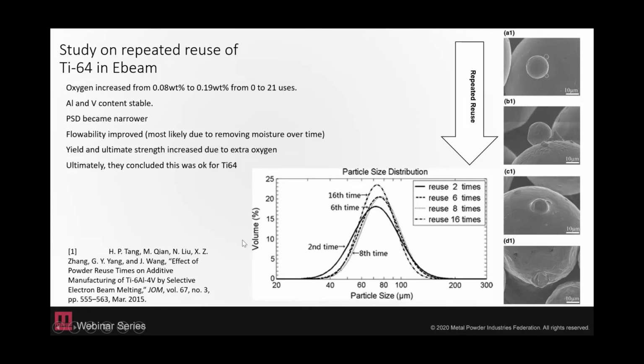So getting back to some issues with E-beam, here's just a study on powder quality that was done a few years back. They performed multiple builds with the same powder, and then they analyzed the powder after each build. So this study was being done with Ti-64, which is a popular titanium alloy. And so what they found in the study is that their oxygen did increase from their 0 to 21 uses. Their aluminum and vanadium content was stable, and they did see a narrowing of their particle size distribution.